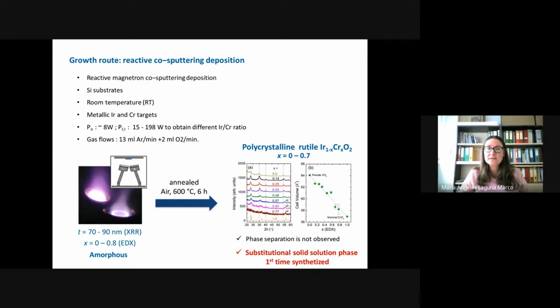Given the practical importance of sputtering for the growth of films in favorable industrial conditions, the films were grown by sputtering. More in particular, the iridium and chromium oxide films were prepared by conventional oxygen-reactive magnetron co-sputtering deposition on silicon substrates at room temperature and from metallic iridium and chromium targets. And in order to get polycrystalline samples, the as-grown films were annealed in air for 6 hours.